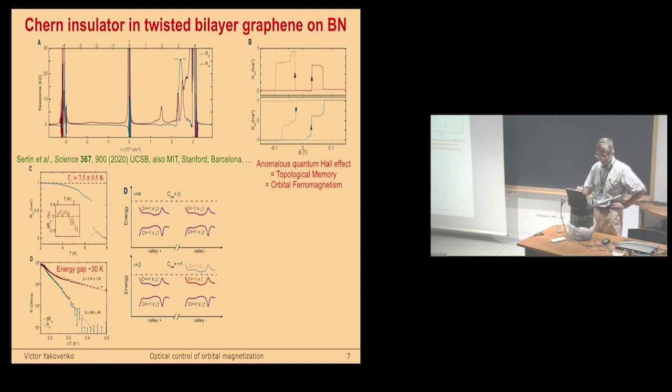This is this situation. But now let's say we decrease the filling factor to filling factor 3. So now we have to partially depopulate those bands. And of course, the system could in principle have partial population, but systems don't like this because of Coulomb interaction. Because of Coulomb interaction, they prefer bands either completely occupied or completely empty. So essentially it spontaneously breaks symmetry between valleys and pushes one band above the Fermi level. So this band is now depopulated and this is populated. So now the system spontaneously breaks symmetry between valleys.